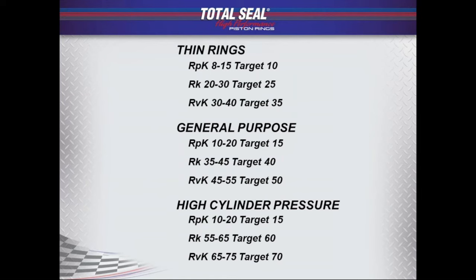So important to keep that RVK number up, to keep that oil retention, to keep that oil trapping, the bearing area, the RK, the RVK, the oil retention area. Those numbers, I see them get flip-flopped so many times. We get into premature wear, bad ring seal, too much blow-by, oil control issues, all the bad things. Keeping those numbers up high assures that proper ring seal. So I just wanted to kind of touch on that.